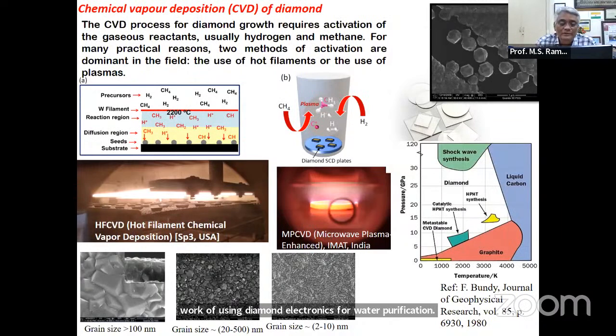Diamond can be grown in 2 ways. It's a CVD process. We use hot filament CVD when it comes to applications related to coatings on machine tools for mechanical wear resistant applications, space applications, where you see the formation of these crystallites. All these crystallites agglomerate, and you see the formation of these layers. So we can control the grain size and call these structures microcrystalline diamond, nanocrystalline diamond, and ultra nanocrystalline diamond. All this depends on the kind of application that you're looking at.